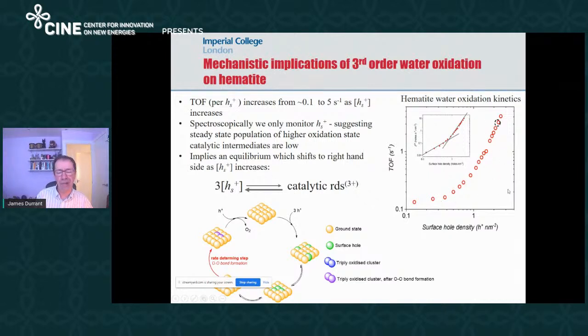This corresponds to approximately when you start to oxidize nearest neighbor metal centers, which is maybe why you start to see a transition from individual holes reacting in this regime where the holes don't see each other to this regime where holes start to find they've got nearest neighbors. What we observe as we increase the density of holes at the surface, we just see more of these states. And so what that suggests is that the only thing we are observing are these holes,